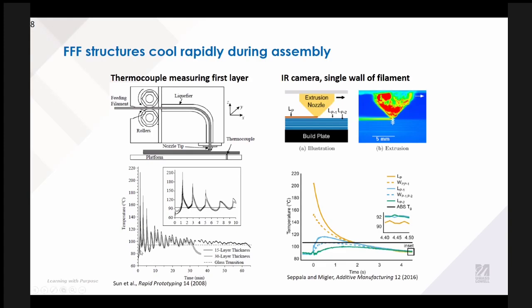One of the key things you'll see in a lot of the graphs that I'll be presenting is that there's going to be some sort of dashed line or straight line that corresponds with a glass transition. Amorphous polymers can exhibit a glass transition, where they go from being in a glassy state to a rubbery state. The way we can think about this is if the polymer is glassy, it's not flowing over time scales that are useful for this manufacturing. It can be flowing over years, maybe tens of years, depending on the temperature. But really, we need to be above Tg in order to have flow.